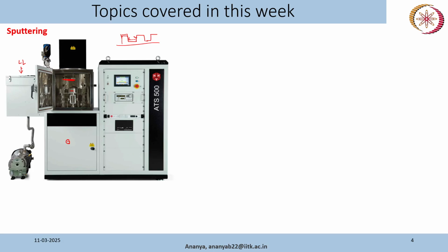Now another advantage, and I'm just explaining these advantages from the slide that was shown in the lecture videos. One point was that sputtering cleans the substrate, and it cleans the target material for deposition. So what we do during sputtering is something called pre-sputtering. In our targets, the top layer of some materials may have oxide formation. Say you want to do a copper deposition, many times the copper target will have a very thin oxide layer, and you don't want to deposit that on your substrate.